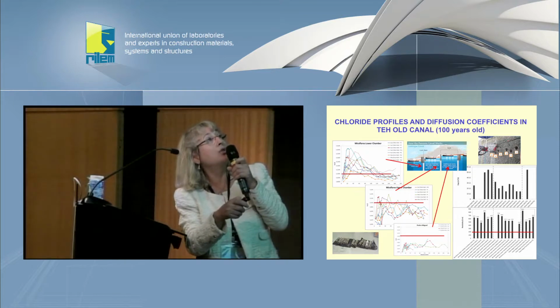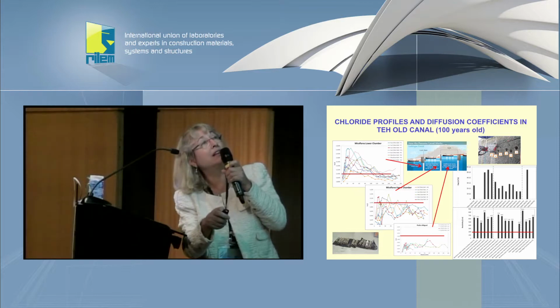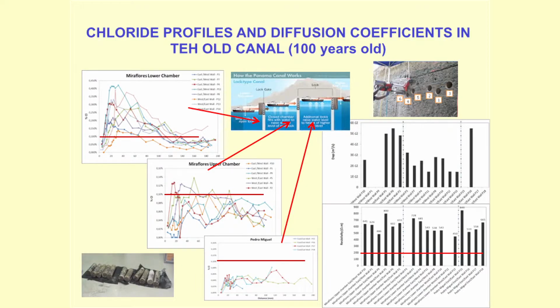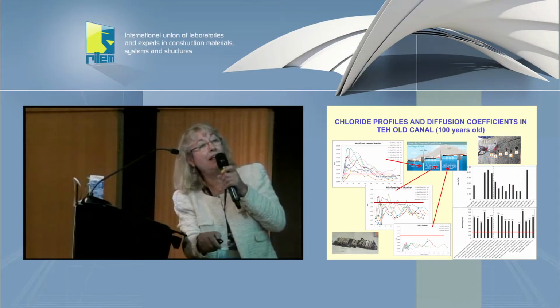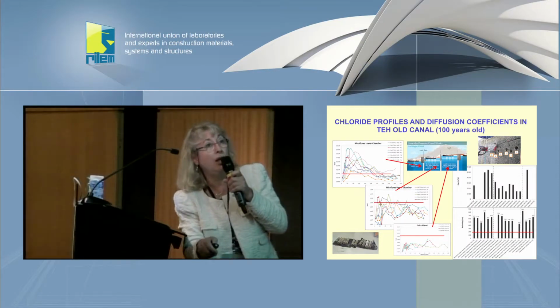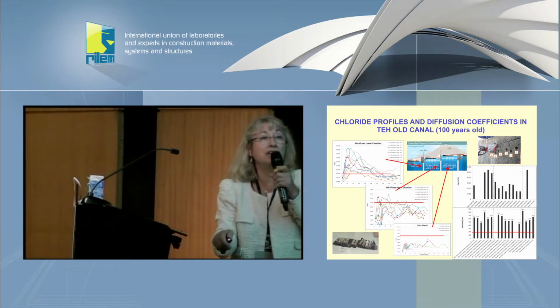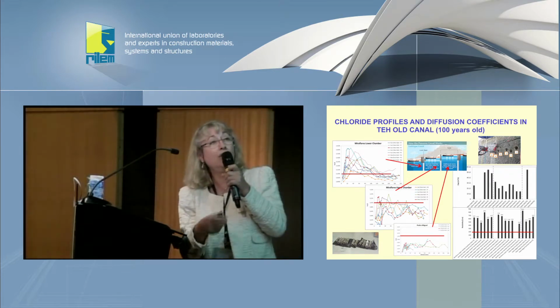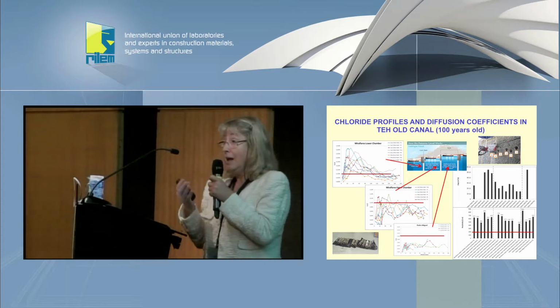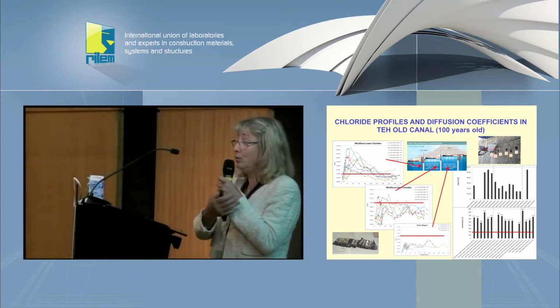The maximum also has different convection zones, and it's clear that in the locks that are near the sea, we have much higher concentration of chlorides. We are realizing that these amounts are similar to what we are seeing in many other cases, and in the intermediate zone there is a much lower amount of chlorides, and of course in the fresh water of the lake there are no chlorides at all. We were analyzing the diffusion coefficient and the surface concentration in order to make a statistical analysis.